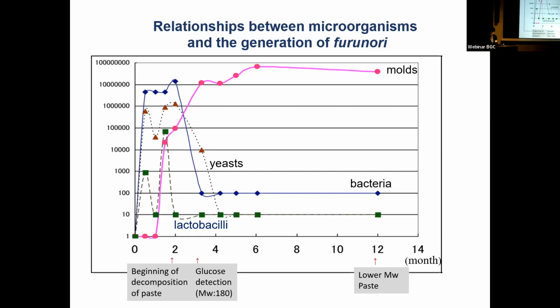Glucose, a unit of starch polymer, has a molecular weight of 180. When molds assimilate starch, they generate enzymes called alpha amylase that decompose the starch into glucose and saccharides. In addition, some microorganisms also decompose saccharides into organic acids. Thus, all of the furunori samples had low pH values or high acidity. Based upon these results, I was able to summarize the process by which furunori was generated as follows.